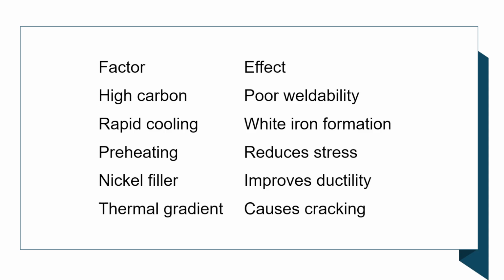So some of the key points: high carbon content means poor weldability. If we do rapid cooling of the cast iron during welding, it will form white iron. With preheat treatment, we can reduce the stresses. Nickel filler improves the ductility, and thermal gradient causes the cracking. A higher thermal gradient results in high crack formation.